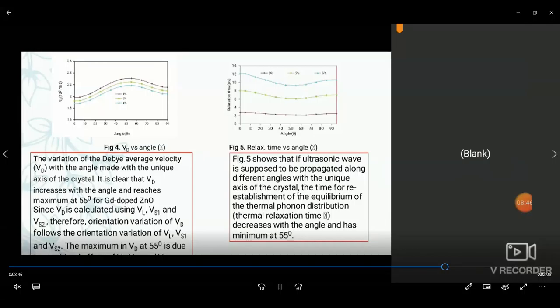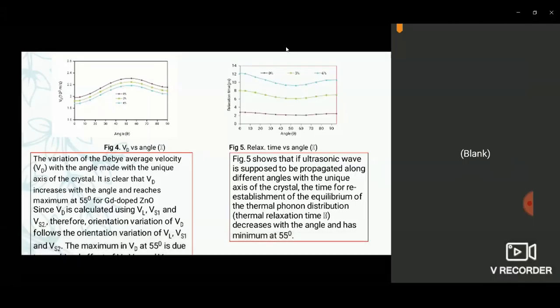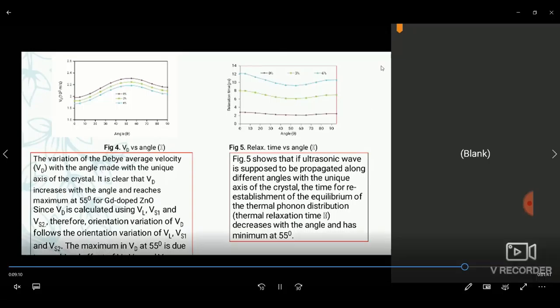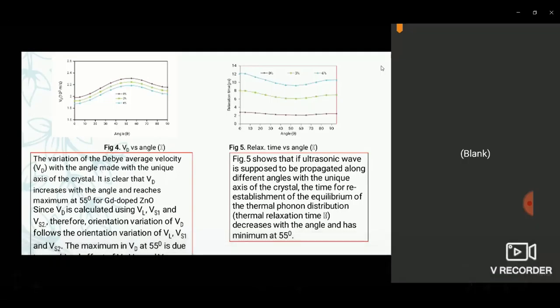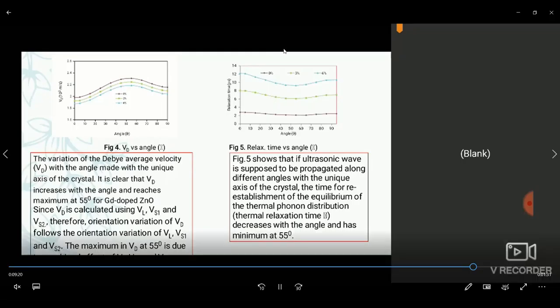Conclusion. The principle established on the simple interaction potential model remains valid for calculating the higher order elastic coefficients of Gd-doped zinc oxide nanorod. The elastic properties of the Gd-doped zinc oxide nanorod imply that it is mechanically stable. The thermal relaxation time is found to be of the order of picoseconds for the hexagonal structure, and tau has the smallest value at angle theta 90 degrees, at which the time to re-establish the equilibrium distribution of phonons is minimum for wave propagation in that direction.